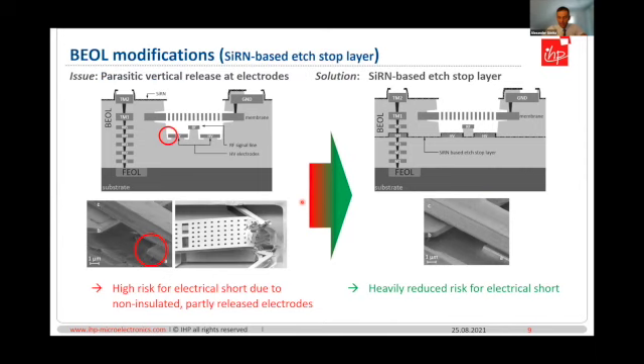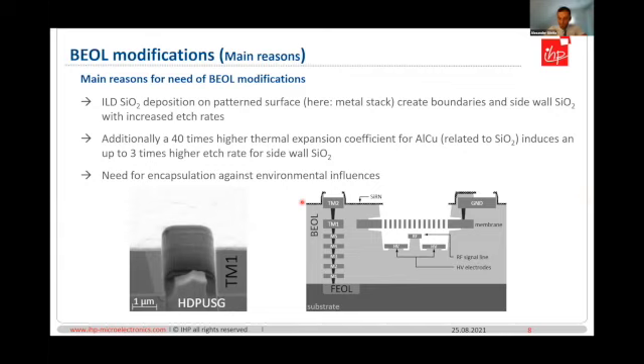Before I start with the backend of line modifications, I want to highlight that every modification is based more or less on the following facts. The ILD silicon oxide deposition on patterned surfaces could create boundaries and sidewall silicon oxide with increased etch rate. Additionally, a 40 times higher thermal expansion coefficient of aluminum copper related to silicon oxide induces an up to 3 times higher etch rate for sidewall silicon oxide. Finally, there is a need for encapsulation against environmental influences.